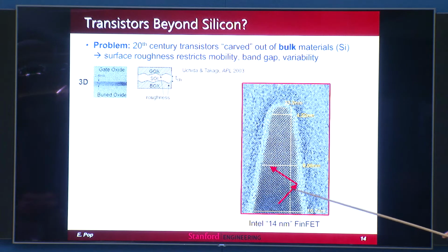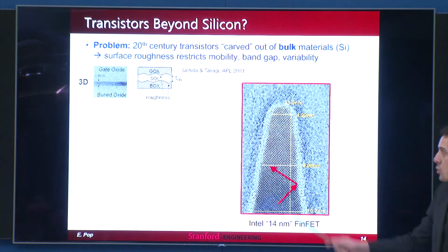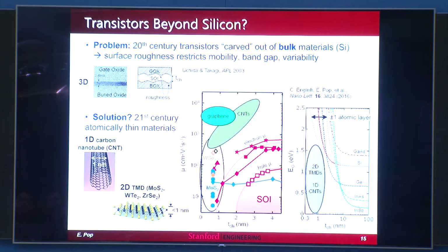But if you're an electron that's rattling around this fin, actually the transport is out of plane, so you're going to be scattering on these interfaces. You can imagine that. And this is my, obviously, very crude attempt at showing electron scattering. For silicon on insulator films, there's work going back at least 15 years, to Ken Uchida and Shinichi Takagi's work, looking at essentially surface roughness limited mobility in very, very thin, down to 2 nanometer silicon films. So this has been known as a limiter for very thin silicon for a while. And it is a problem in FinFETs as well.